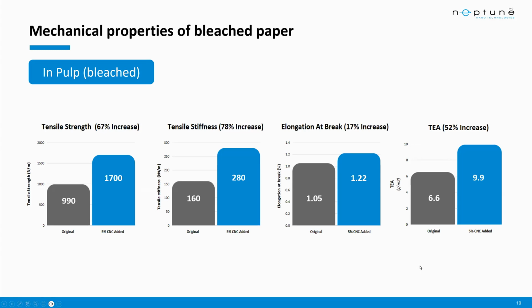So here is what gets more interesting. Now, usually when we increase the strength and stiffness of something by adding an additive or a filler, the material will actually end up being a little bit more brittle. So toughness metrics such as elongation and energy absorption tend to really suffer. However, this was actually not the case with cellulose nanocrystal. We saw an almost 20% uplift in elongation and also a greater than 50% uplift in tensile energy absorption. So this actually makes cellulose nanocrystal a really unique additive that improves the physical and mechanical performance of the paper in an all-round fashion.